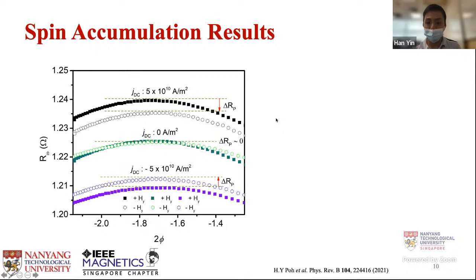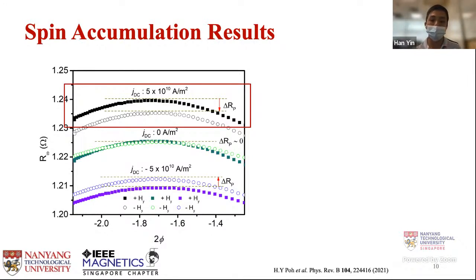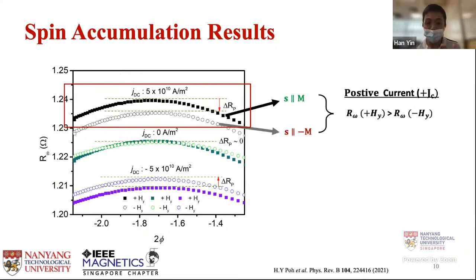So let's take a closer look at the top two graphs in the red box over here. Since the current is injected in the plus X direction, the spin accumulated will be in the plus Y direction due to spin Hall effect. Therefore, the spin S will be parallel to M for the first graph and anti-parallel for the second graph. Just like I mentioned earlier, if the spin is parallel to M, the voltage will increase and vice versa. Here, we can see the amplitude of R omega in positive field to be higher than R omega in negative field. This is because of the alignment of the applied stationary field.